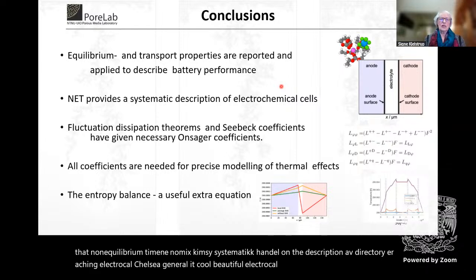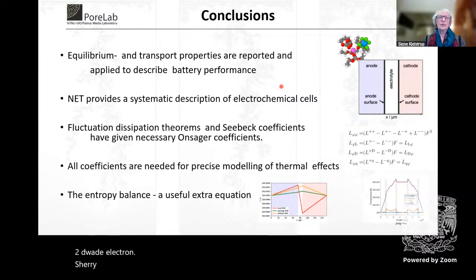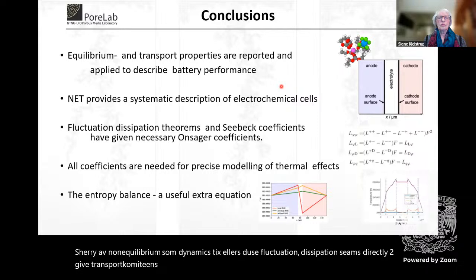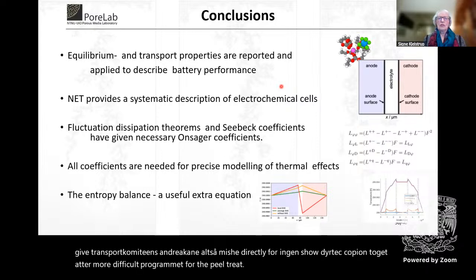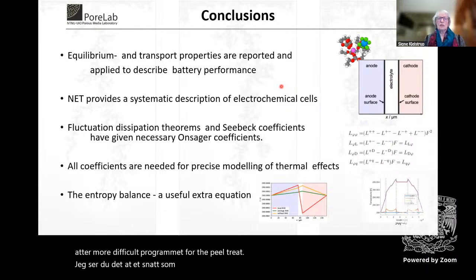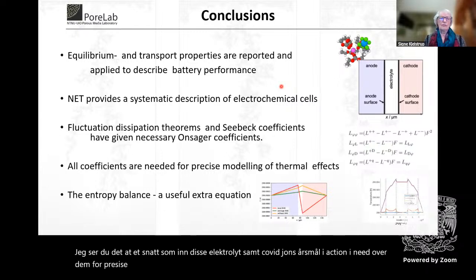Electrochemical systems are always layered and difficult to deal with at the electrode. The theory of non-equilibrium thermodynamics allows us to use fluctuation dissipation theorems directly to give transport coefficients. And you can also measure directly, for instance, I showed you the Seebeck coefficient, to get at a more difficult parameter, the Peltier heat. And I showed you that with this electrolyte, it is not so that some coefficients are small. We actually need all of them for precise modeling of thermal effects. And then as a side benefit, I talked about using the entropy balance for the benefit of modeling. I think it is an underused opportunity.